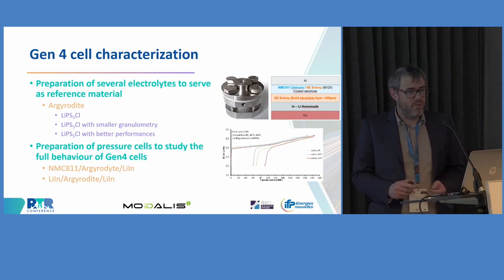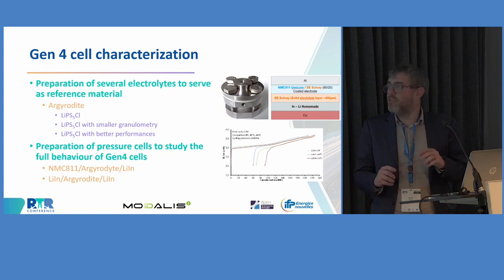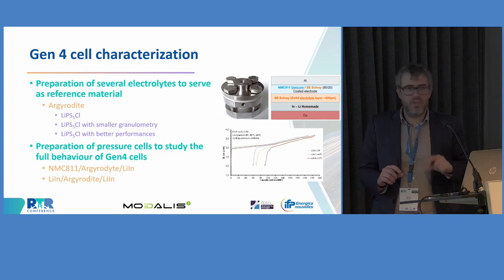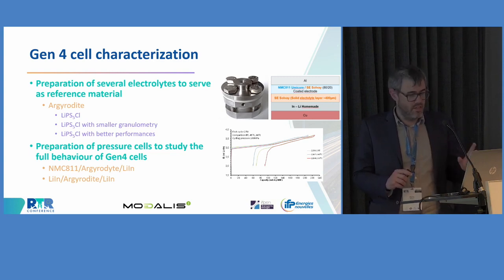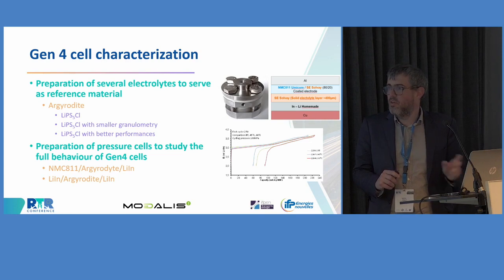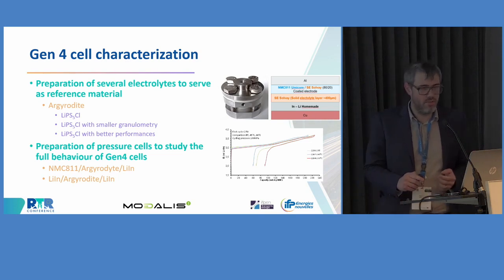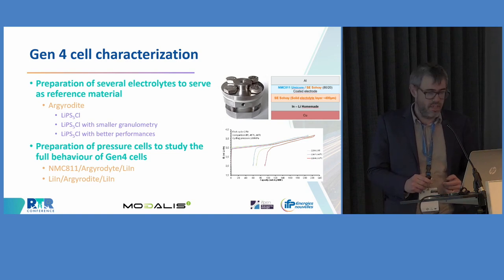So as for Gen 3B, we have dedicated cell characterization for Gen 4 using pressure cell. The reference material we use is argyrodite. We will have three types of argyrodite: a nominal one that we are using currently, a second one with a smaller granulometry, and a third one with better performances, in order for our colleagues from DFT and ab initio calculation to see whether they are able to simulate the change in electrolyte formulation with their models and understand the new behavior that we can monitor experimentally.